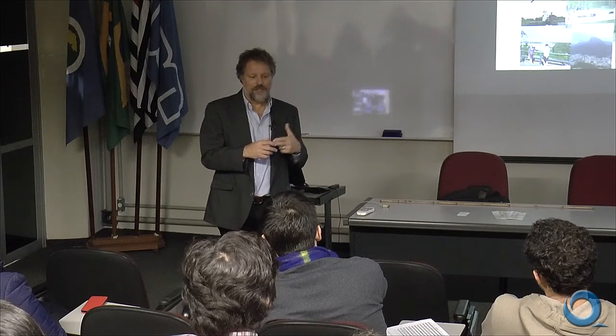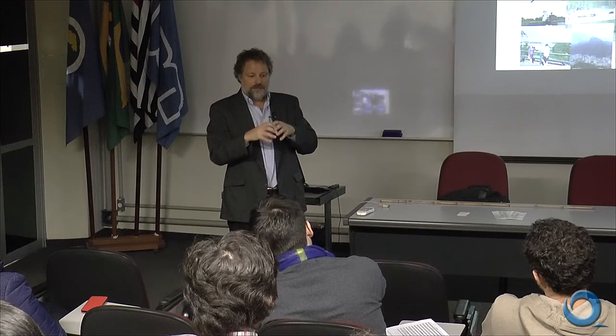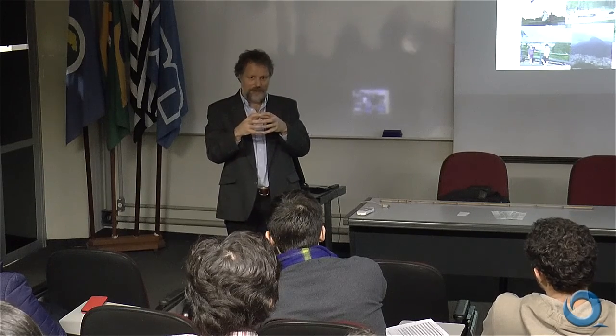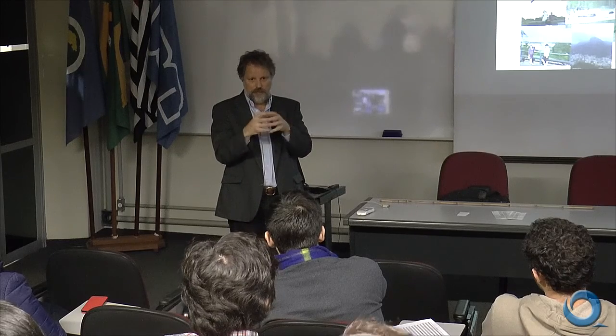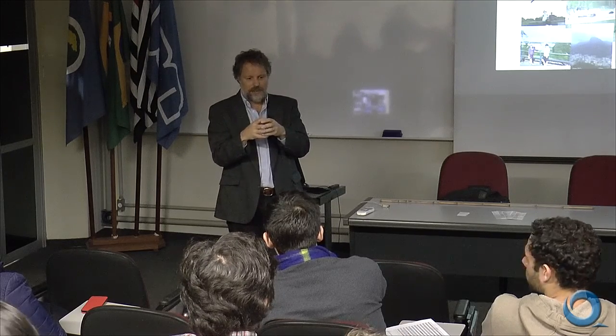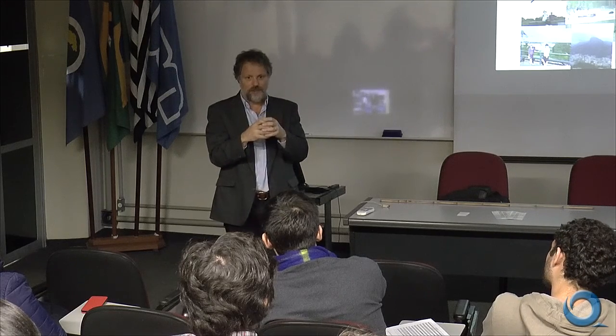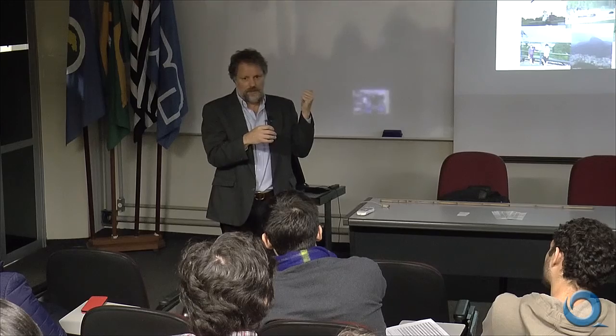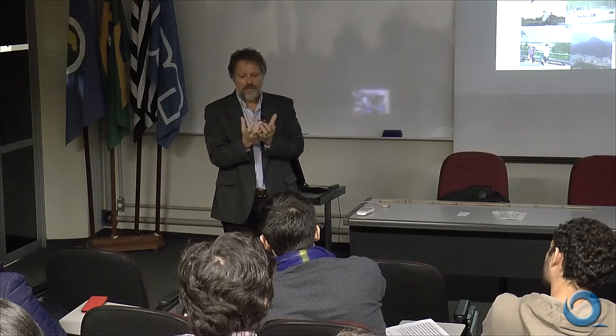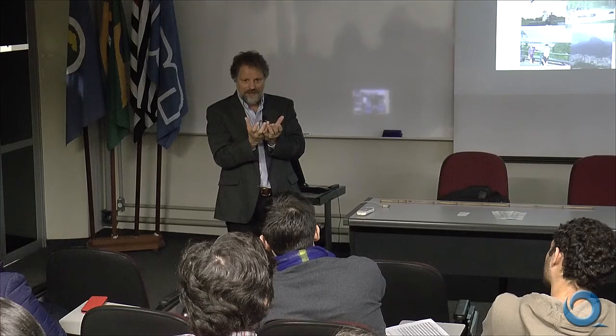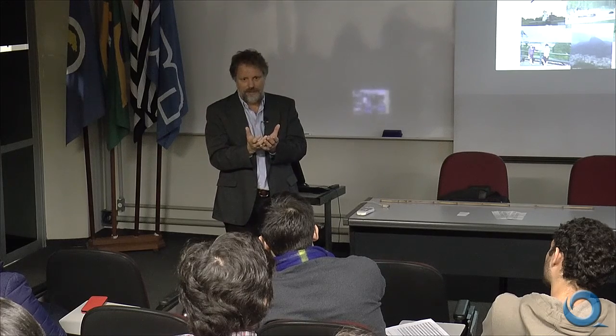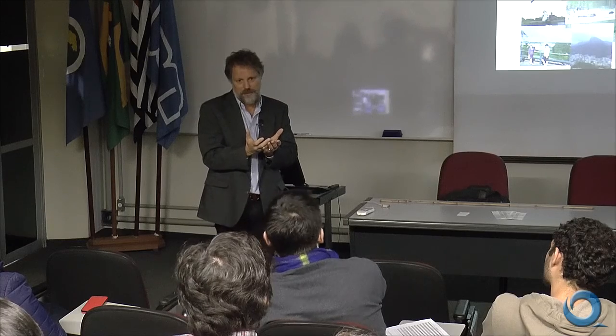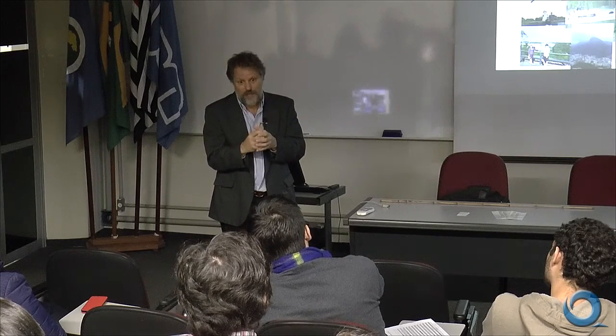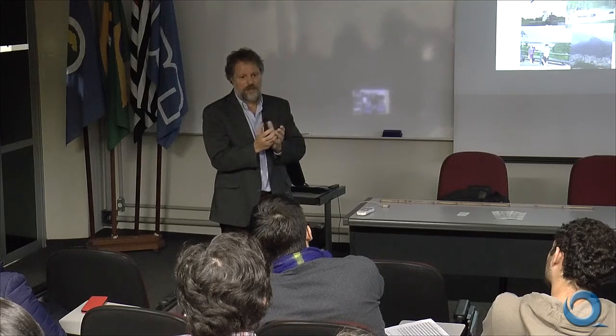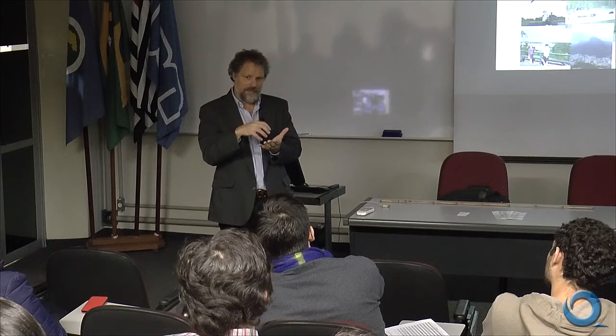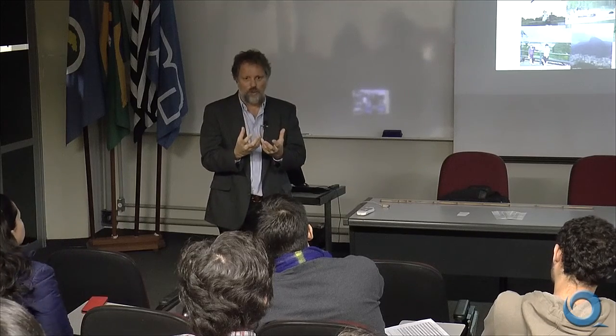Right now, my impression is that the cartoon of that spherical nanoparticle with a hydrophilic shell and a hydrophobic core is not really accurate. It's not accurate in solution, but it's certainly not accurate on these once they're adsorbed onto the surface. That hydrophobic structure seems to be really accessible, and that cationic hydrophilic structure does not seem to be very accessible. Now that could be changed perhaps, but with the materials we're using right now, it looks like the analytes are really accessing that hydrophobic core region.